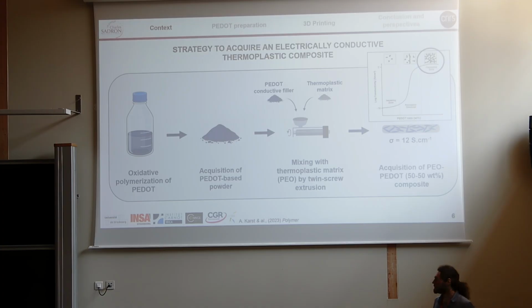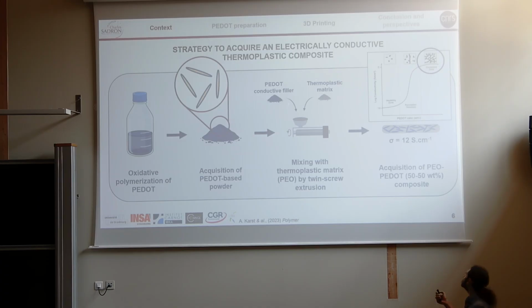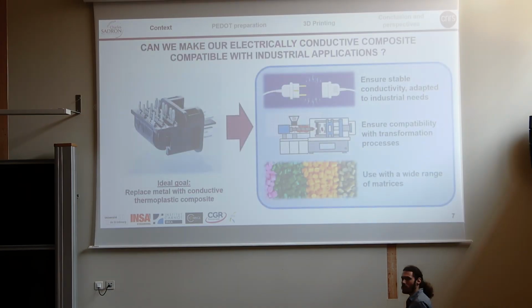Additional work was conducted to increase the aspect ratio of the particles by doing supported polymerization on clay particles in order to reduce this percolation threshold. The results showed that it didn't work as well as we would have wanted, but it still led to a 50% reduction in the use of PEDOT, because the particles are 50% clay and 50% PEDOT, and offer the same conductivity. So this is the starting point of my project with the following question: are we able to make such material compatible with industrial applications, with the ideal goal to replace the metal in those parts with our composite? And for that, we need